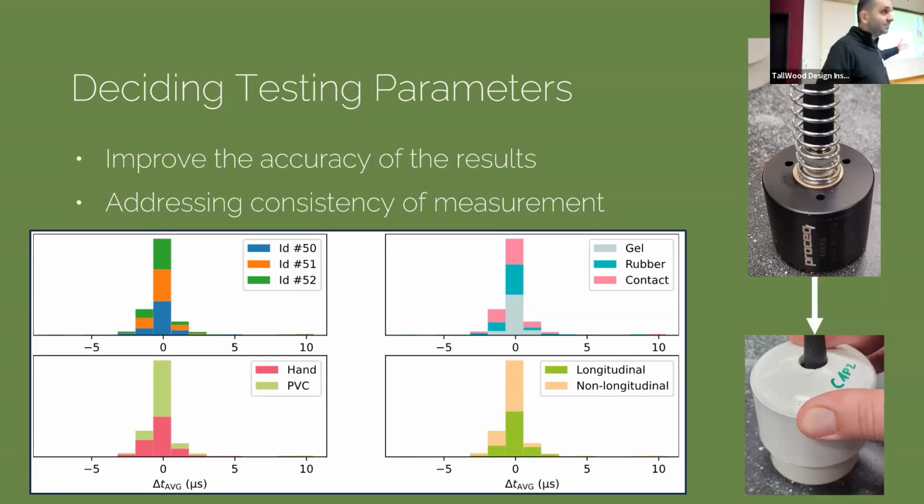In this case, we are using cheap, affordable sensors, but then the problem is we have to measure every point manually. And there are some factors affecting the accuracy and consistency in the measurement. One of them is, when you're applying the sensor by hand, how much pressure you put on the sensor. And the coupling between the sensor and the substrate hugely impacts the collected signal.